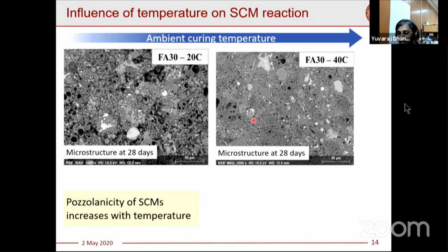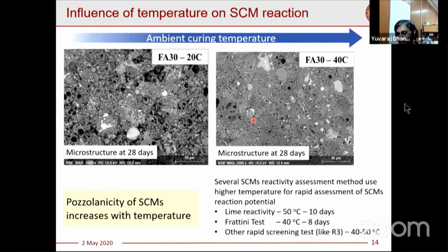So we can naturally think of why a lot of rapid assessment test methods, like the one Pranay talked about, chose to have higher temperature to assess the SCM characteristics at a much faster pace. For example, the R3 standardized test of lime reactivity assesses the strength development of mortar by 10 days at 50 degrees Celsius. the Frattini test uses 40 degrees Celsius, and other rapid screening tests are done at either 40 or 50 degrees Celsius. In order to maximize the benefit, use of SCMs will be beneficial in steam cured conditions, because the reaction of the SCMs gets accelerated because of the temperature.